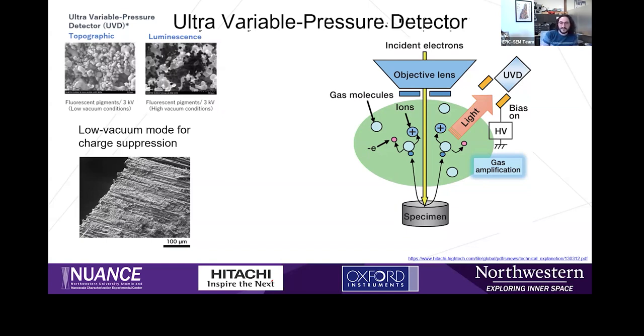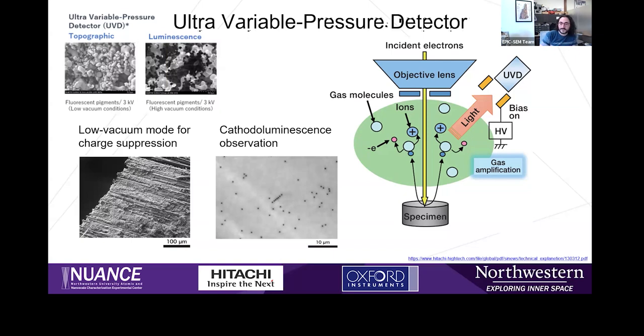Alternatively, the bias on the front of the UVD can also be turned off, which will stop attracting all of the electron ion cascade and light signals from this cascade, and instead starts exclusively collecting the light from the cathodoluminescence, which comes directly from the sample. So you can essentially turn the UVD into a CL detector. And this can help you look at the crystallinity of your sample, find defects and impurities, as well as help you study materials' optical properties, among other things.